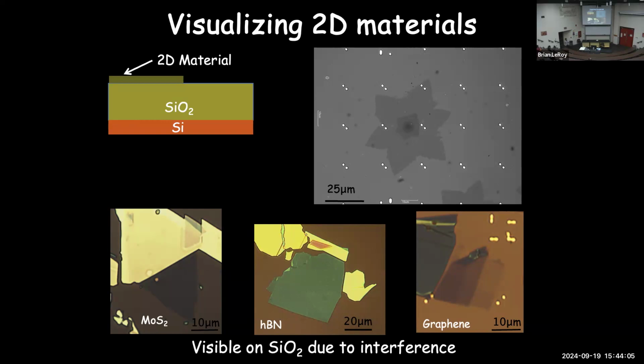They come, though, in different colors because of their different optical properties. It's very hard to see, actually, here. The molybdenum sulfide is down here in the little triangle here. Boron nitride is a much wider gap material. It shows up as more of a green color, whereas the graphene shows up more as a purple color in the microscope. And so what we can do is identify the materials here.